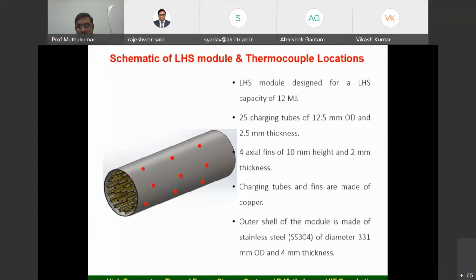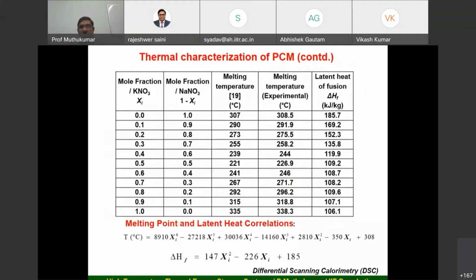So this is the thermocouple position, and these are tubes and thermocouple positions. So we have thermocouples at different axial locations and different radial locations also. These temperature data can be used to analyze the movement of the PCM during the melting. So we have done the detailed characterization. Here we have just taken a 2 component salt like sodium nitrate and potassium nitrate, and their composition can be varied. And see here the melt fraction and the respective compositions, and the latent heat also. So finally, the melting temperature can be expressed as a function of composition, the percentage of composition, and similarly enthalpy also can be expressed.